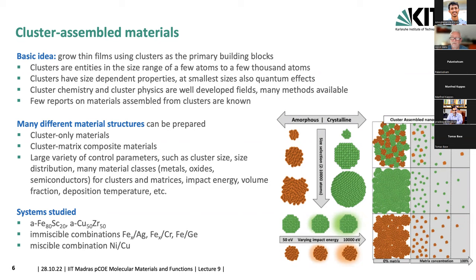And this gives you an idea of which clusters we have studied so far. We have done amorphous clusters like these here, or crystalline clusters like these here. For example, the amorphous one was iron 80, scandium 20. This, as well as copper 50, zirconium 50, are glass-forming compositions, so we can grow them as amorphous clusters already in our system. We have done immiscible combinations of matrix and clusters, for example, iron in silver, or iron in chromium, or iron in germanium. But we have also done a miscible combination, like nickel clusters in copper.